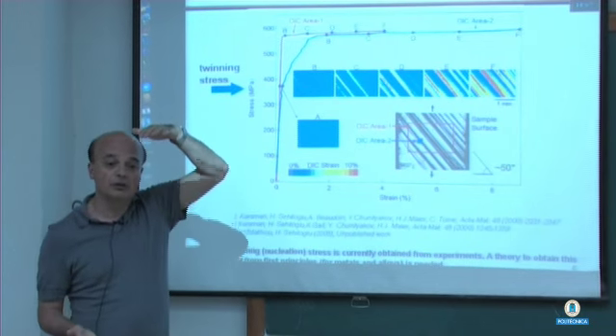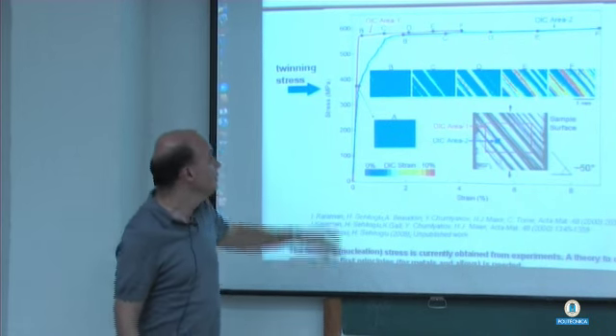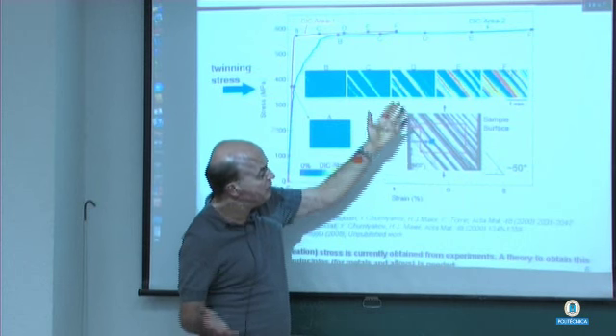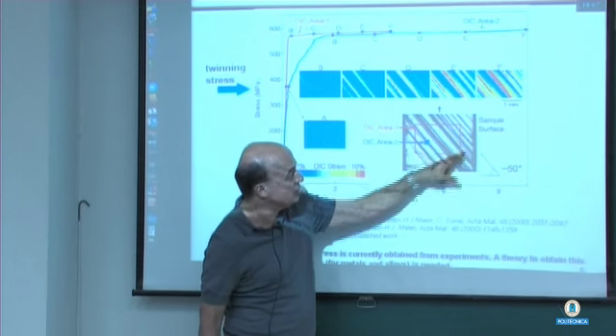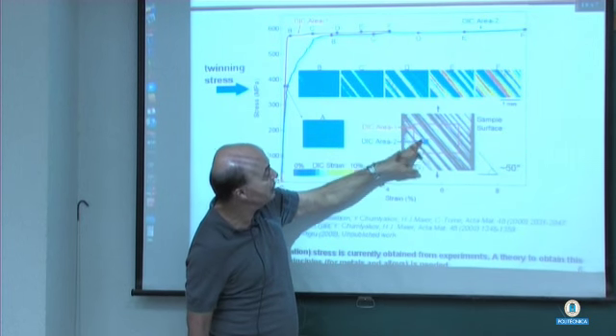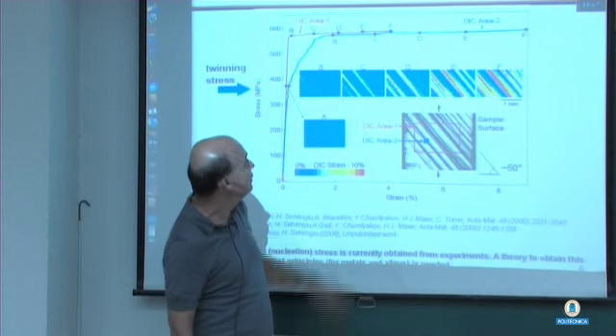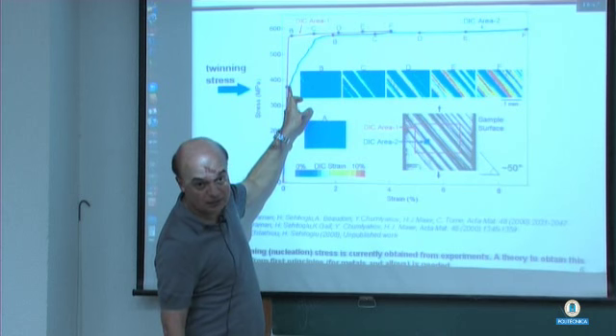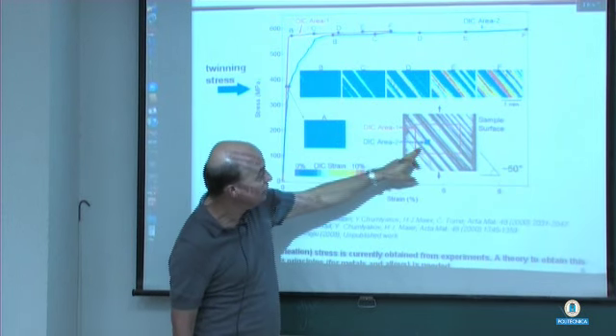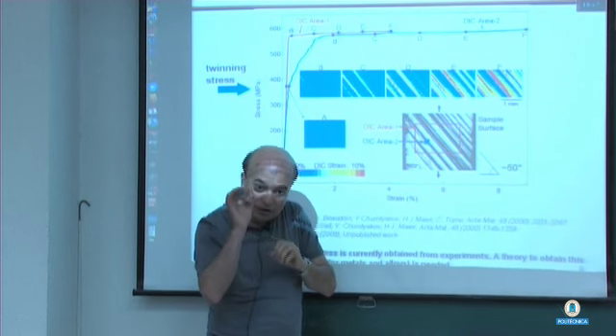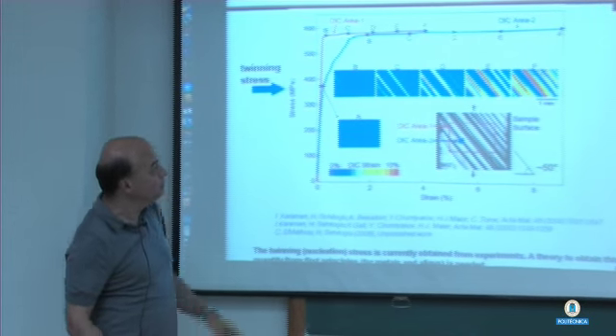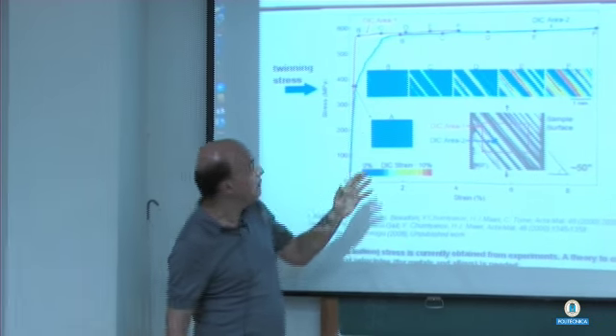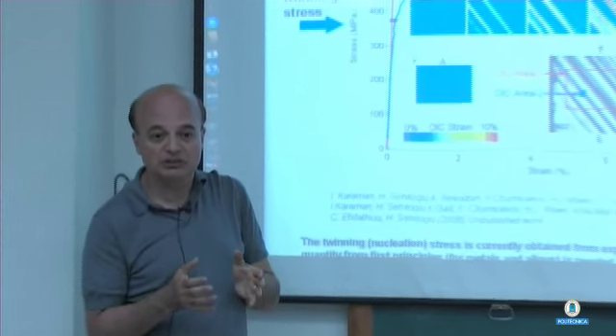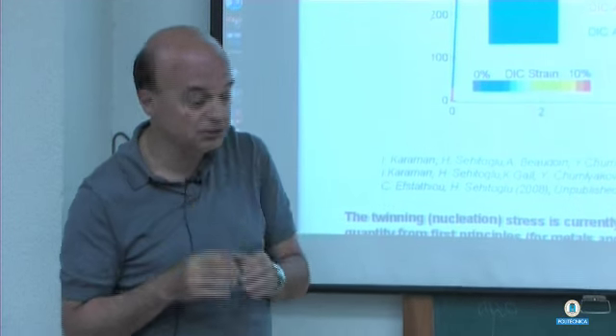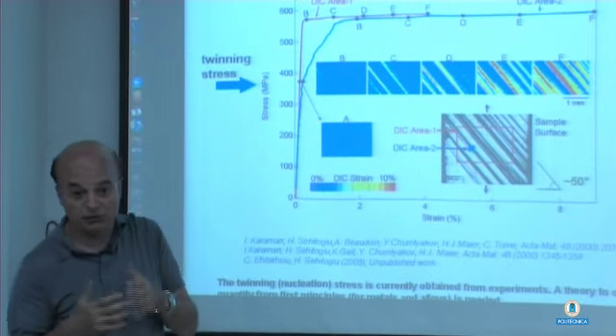Now, if you made measurements at a global scale, like with a large extensometer, you'll get the red one. Even with a small extensometer, if you're looking at an area which is large like this, you'll get the red curve. If you're looking at a smaller area, at a higher magnification, you'll see that the onset of twinning starts at a much lower stress, right? But the deviation starts really here. This is digital image correlation area 2, which is encompassing that twin. So the two purposes of this diagram are to show that, number one, if you want to measure twinning stress experimentally, you may have to look at fine scales in your strain measurements. Number two, ideally you want to be able to predict this from first principles, and some of this is published work.